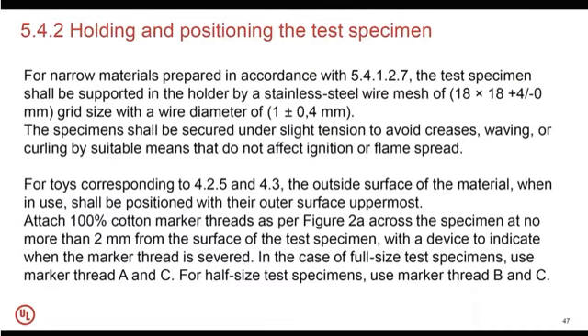So for toys corresponding to 4.2.5 and 4.3, the outside surface of the material when in use shall be positioned with their outer surface uppermost. And also there is the need to attach 100% cotton marker threads as indicated in figure 2A across the specimens at no more than 2 millimeters from the surface of the test specimens with a device to indicate when the marker thread is severed. And in the case of full-size test specimens, there is the need to use marker thread A and C, while for half-size test specimens, there is the need to use marker thread B and C.